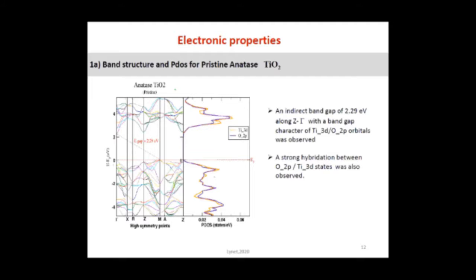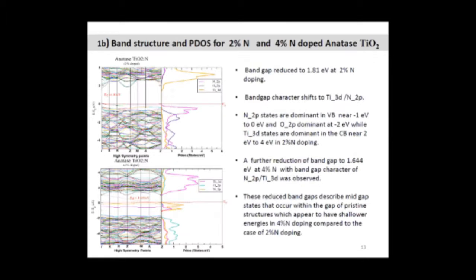When we doped this at 2%, we found that the band gaps reduced. At 2%, it reduced to 1.81 and further reduced at 4%. This reduction was attributed to nitrogen, because if you look at the PDOS, you can see that nitrogen 2p states are the ones contributing to the reduction of the band gap.